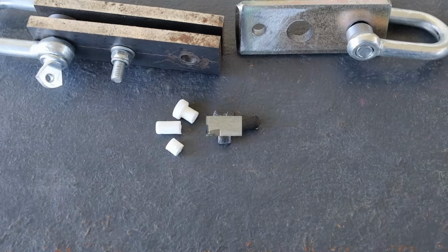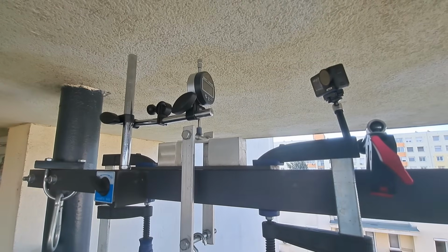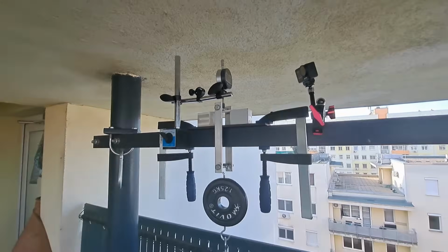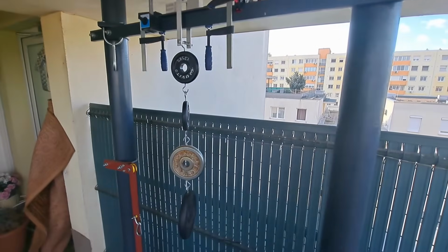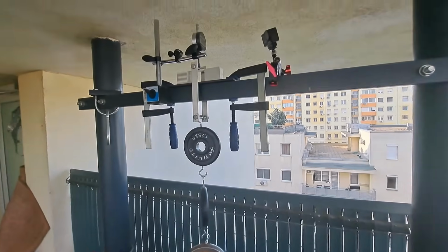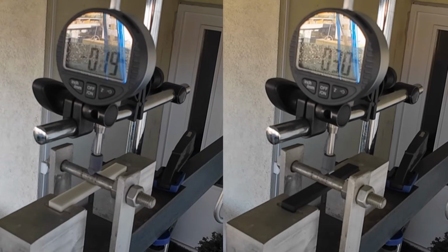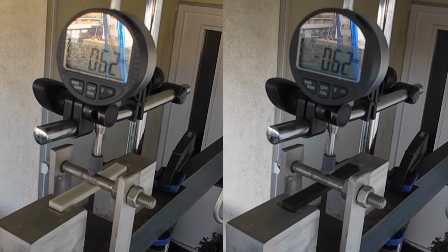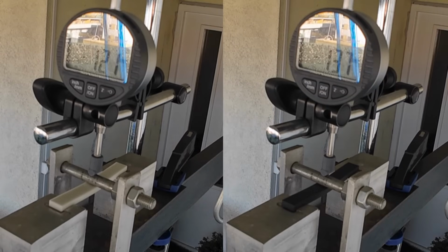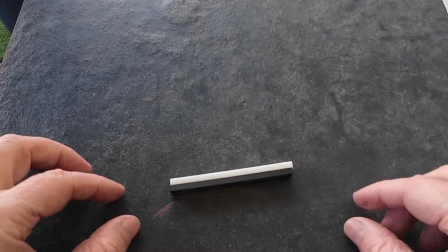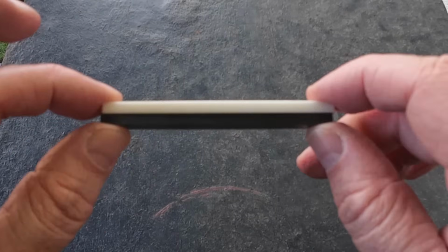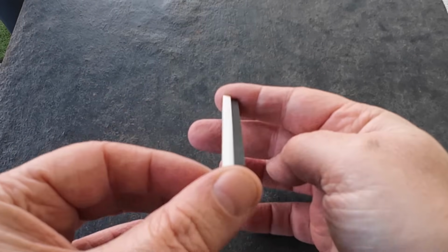And now the 3-point bending test. Here you can see my equipment where all loads are placed on it, but I will place them one by one. And I will measure the deformation after 30 and 60 seconds. It was interesting to see more initial deformation on glass fiber filament, but later on higher loads, more deformation on carbon fiber material and some creeping too. And after this I can hardly see any deformations on these objects.